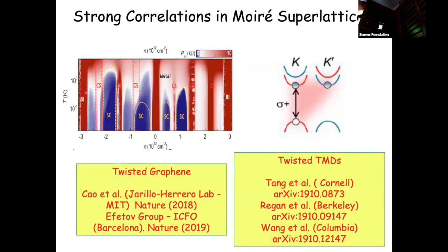So here's one contrast between graphene multilayers, this is actually twisted bilayer graphene, and transition metal dichalcogenides. This subject started experimentally, as you all know, from the discovery of this phase diagram by Pablo Jarillo-Herrero at MIT. This is actually data from Dmitri Efetov at ICFO, but it shows resistance as a function of temperature with all this interesting structure, in particular superconducting regions, and insulating regions, where you don't, in a single particle theory, expect insulating behavior. And it's characterized electrically, so resistively, by measuring resistance.